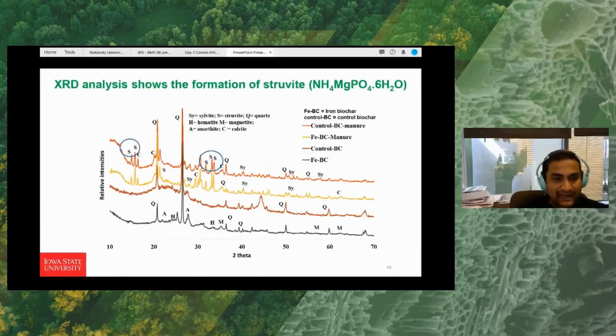So in this slide, we did the XRD analysis of the material we recovered after the breakthrough curve, and it shows the formation of the struvite mineral on the biochar surface. There are 4 samples here: control biochar manure, iron biochar manure, control biochar, and iron biochar.